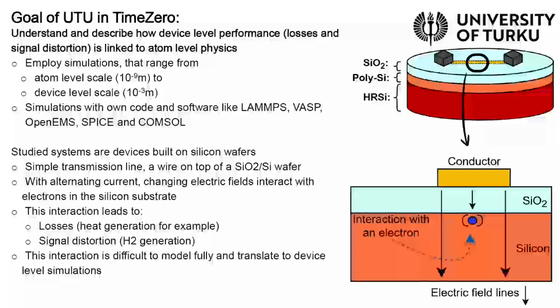It's very challenging, but the atomic level simulations have been carried out by various tools, and then they are propagated to studying a transmission line on a layered structure of oxide and silicon, and studying the electric field RF signal effect on the charges at the interface, and then leading to losses and the harmonic generation.